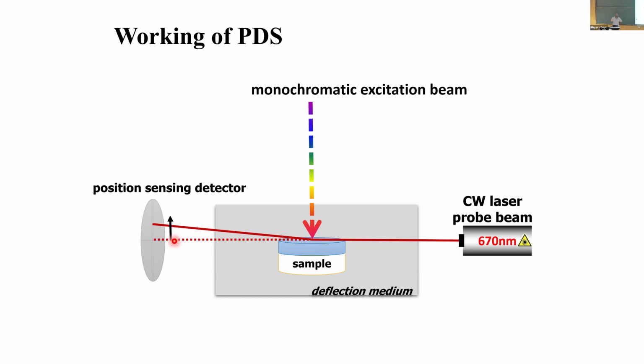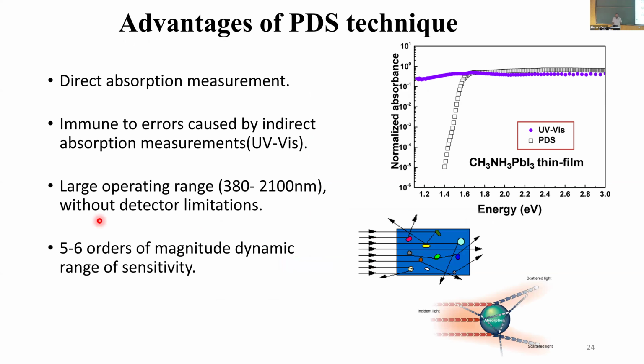So here what happens is you need multiple detectors to measure the absorption in a traditional spectrometer. Here the detector is simply looking at deviation for the light that is incident on the sample. So you are detector limitation free in this measurement compared to the traditional way of measuring absorption. So we can then measure a large range of absorption, the range which we can measure is 380 to 2100 nanometers, and this comes from the whole optical setup that we have, not a detector limitation, it's the excitation limitation.